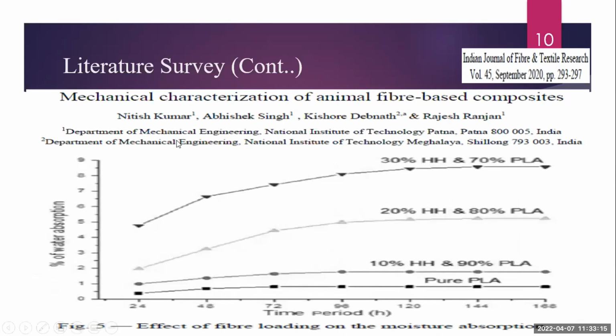Nitish and his team also tested the water absorption behavior of this composite. They found that as the percentage of horsehair fibers in the polylactic acid increases, the water absorption also increases. So it means the water absorption behavior depends on the fiber percentage in the composite.